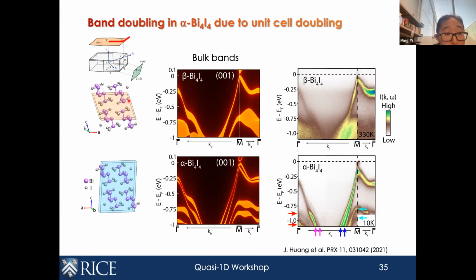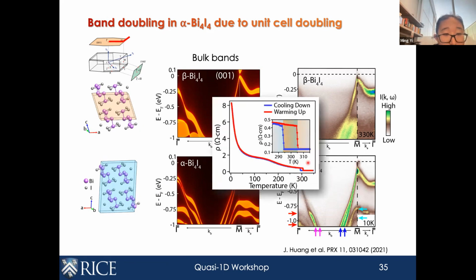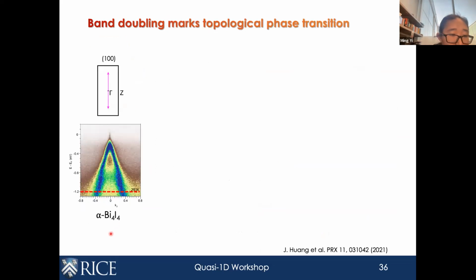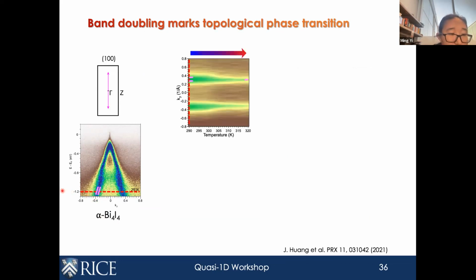Having confirmed that, we want to look across the transition, close to where this transition actually happens around 300 Kelvin. Unfortunately, at 300 Kelvin, there's a lot of thermal broadening, which means that it's hard to actually resolve the two separate bands. However, even though we cannot resolve the splitting of the two bands at that high temperature, when the bands double, you expect that this peak will broaden, right? So with that, we can, for example, trace the horizontal cut here, at this energy.